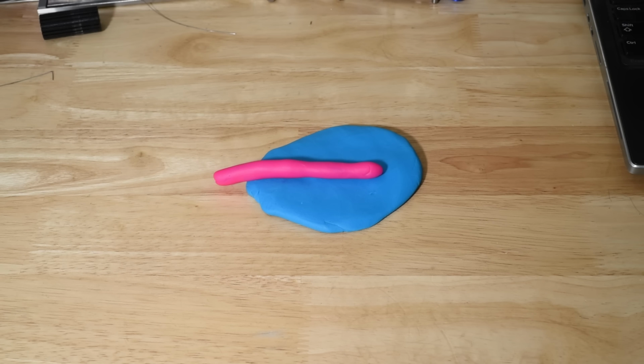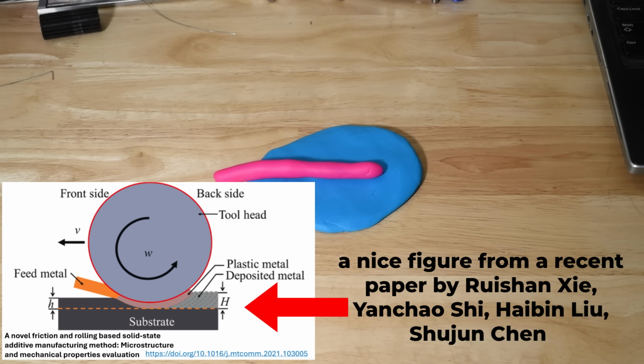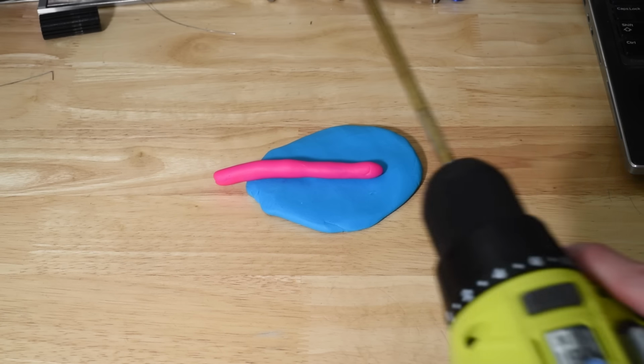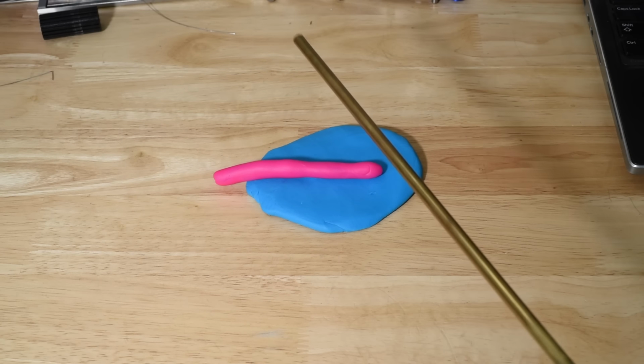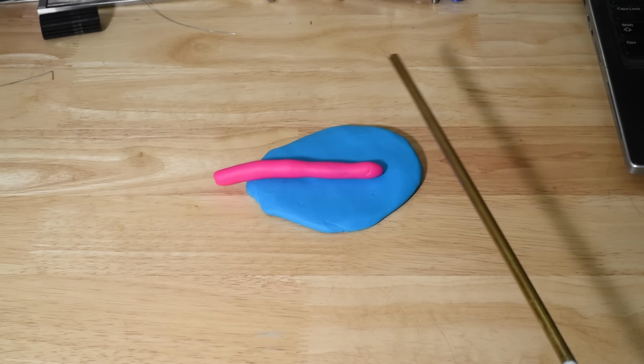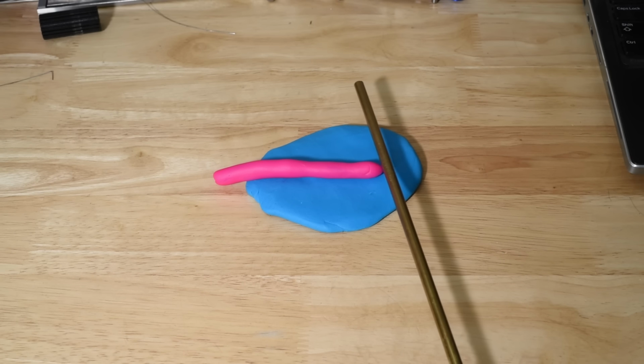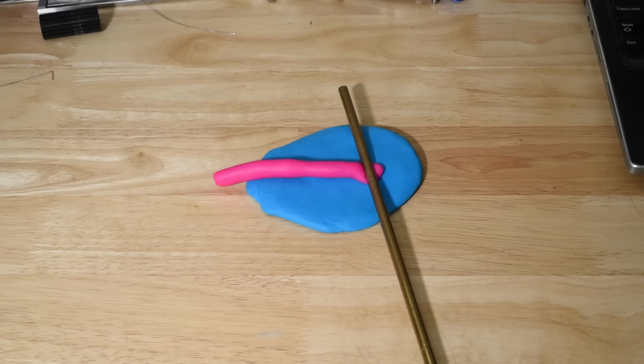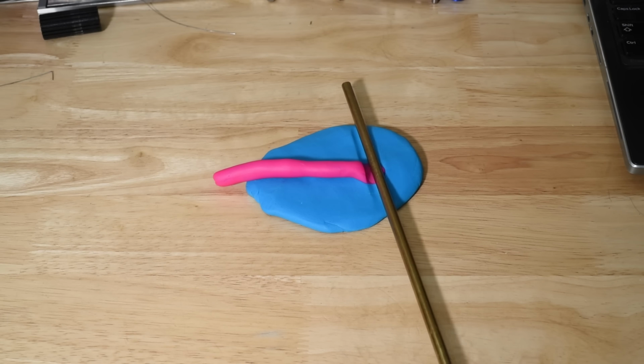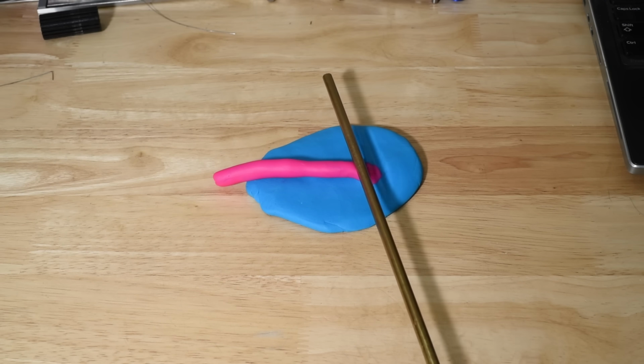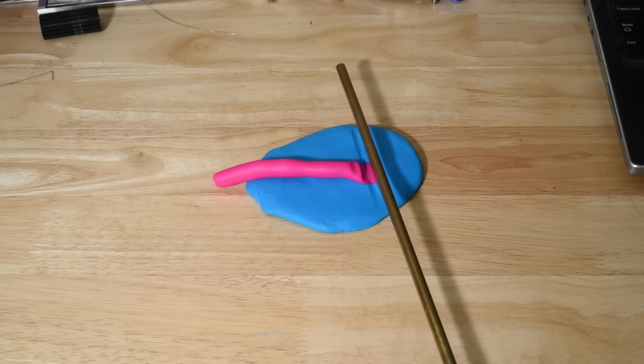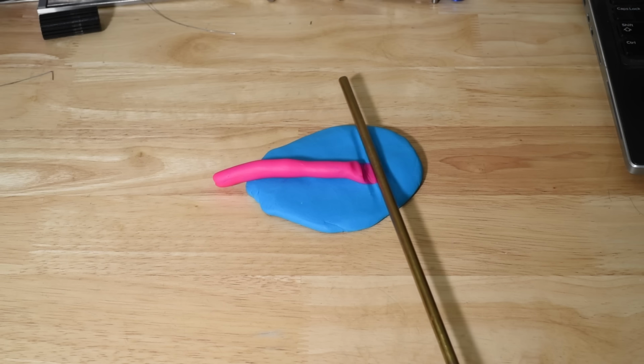So Rotoforge uses a process similar to additive friction roll bonding. To show what that looks like, I have a substrate made of Play-Doh and a piece of Play-Doh that I want to try to bond to it using that process. So I have here a shearing tool, which is a piece of brass chucked in a drill. And what we're going to do is, rather than trying to use a lot of downforce to try and deform one into the other, which we can only do locally and which needs relatively large amounts of force, or trying to rely upon some heating process where we heat and locally melt what we're trying to bond to the substrate, or the substrate itself,